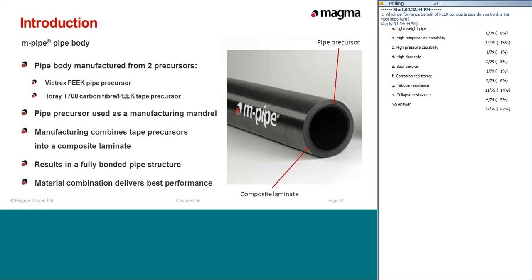So some more details then on the pipe body itself. M-pipe pipe body is manufactured from two precursors. The first precursor is the pipe precursor itself, which is extruded from VICTREX PEEK. Then the laminate itself is built from a carbon fiber PEEK tape precursor. So this tape, which uses Toray T700 impregnated with PEEK, is used to build up the laminate.